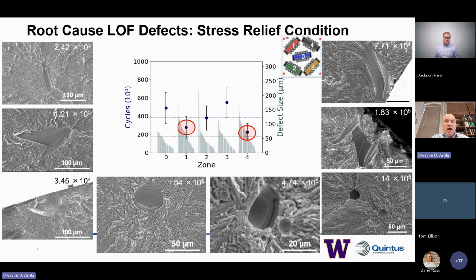What's it caused by? Well, actually, we find also if we superpose defect size within those particular zones, we see we have larger lack of fusion defects which are present in 1 and 4 relative to that in 2 and 3. Examples, of course, are shown here around the periphery. Just some examples in the individual lives that you see for those lack of fusion voids.